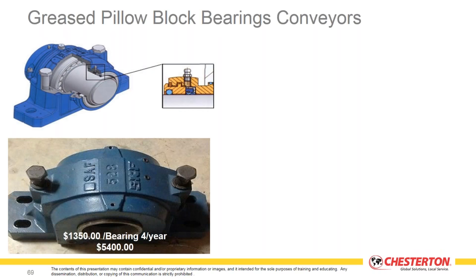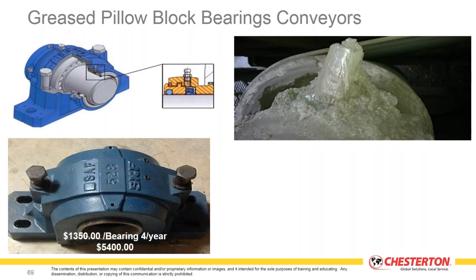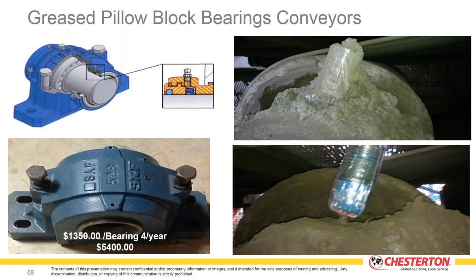So we take a look at the pillow block bearings. Some of the bearings are fitted with a taconite seal outboard, which should be greased to help protect the bearing inside. But we can also do something very imaginative, and that is there are two potential fitting areas just above the seal on the bearing housing. And we have been not only greasing through the center zerk, but also drilling and tapping right above the seal and injecting grease into the seal area of the bearing. We can also put on an automatic lubricator, in this case, the Chesterton Lubricup, to continuously supply a small amount of grease to that bearing on a daily basis, which helps exclude the abrasive contaminants from getting under the seal and into the bearing.